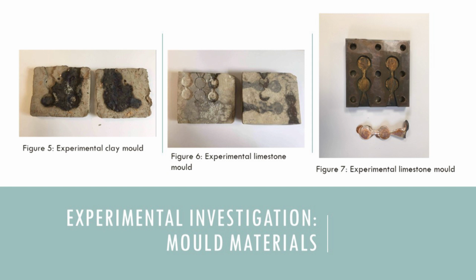For the stone mould, a block of limestone was acquired from the Department of Environmental Science at the University of Liverpool, and I used a small handheld drill to create the indentations and channels, and then the stone mould was dried in the furnace to remove any excess moisture before casting. The bronze mould was created by the engineering department at the University of Liverpool, and the mould was fabricated from a high tin bronze with 12% tin. Evidence from the mould survey demonstrated that Roman moneyers were using high tin bronzes to fabricate their official dies, and it is possible that they also used this alloy for their flan moulds.